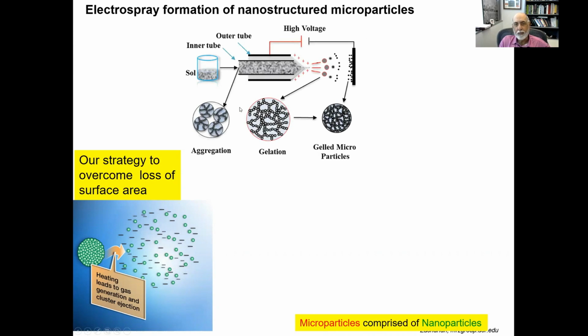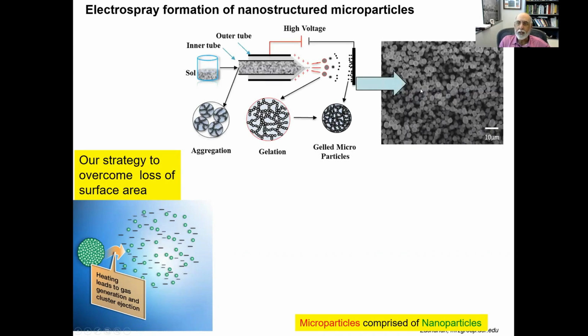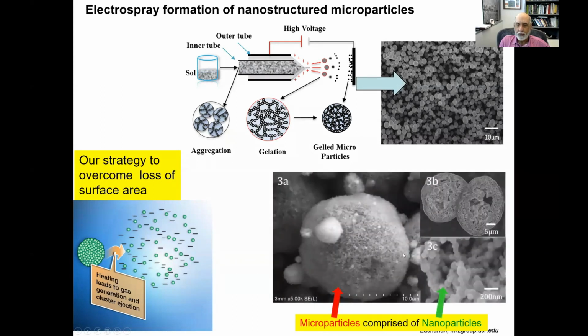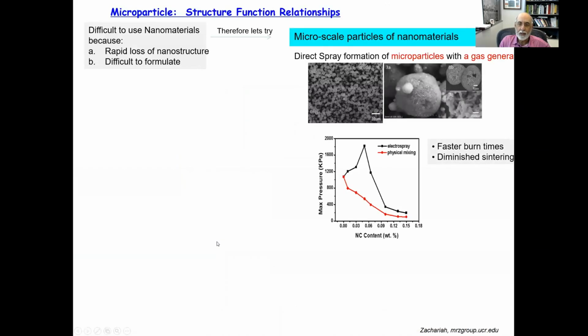And so we have a process to make these gelled microparticles. Essentially, they're large particles that are comprised of nanoparticles. So here's the microparticle, and if I zoom in, they're nanoparticles, but inside there's also a gas generator that acts both as a binder and as a gas generator to puff things out. And this works quite well, actually. Here is the pressurization rate of these materials in their nascent form, and these materials as one of these microparticles. And you can see that the mesoparticle-based materials, as a function of binder content, which is the gas generator, significantly outperform the same chemistry. So the chemistry is the same, it's just the architecture is different.